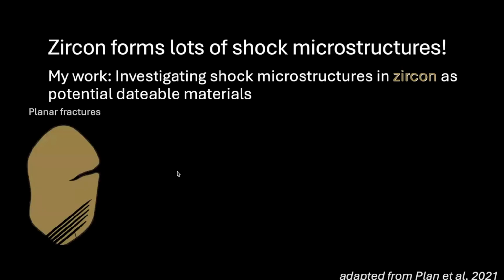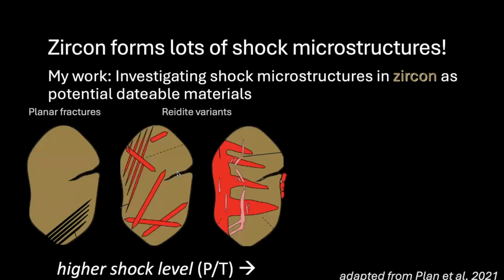So at the lowest shock levels, zircon forms planar fractures. With higher pressures above about 10 gigapascals, it transforms to a high pressure polymorph, reidite. So this is also zirconium silicate, just a different structure. Reidite itself is found in many microstructural variants. I am not going to dive into those in this talk, but I have also done a lot of work on that. So if anyone's interested, we can talk about it later.